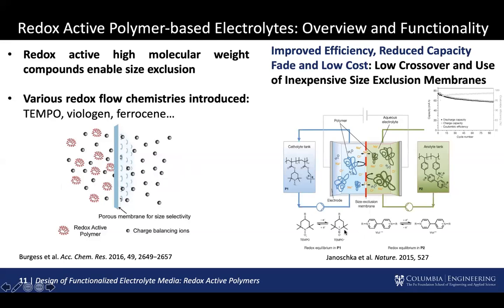And we see these are based on organic species. And what we can see on the top left there is that this battery was actually able to maintain capacity over several cycles, even with the use of a size exclusion membrane. So those polymers were not crossing over, even though the membrane was less selective because of their large structure. So this is, I think, another example of how structures of electrolytes can be used to give some function in a battery.